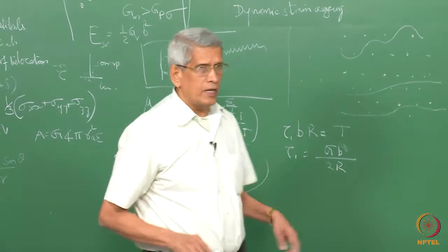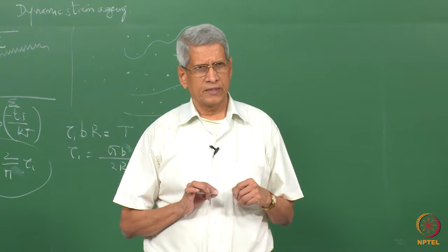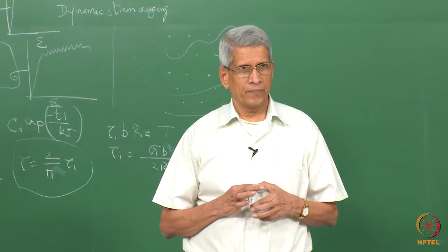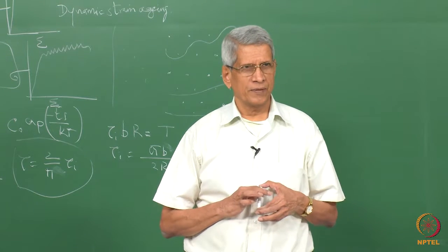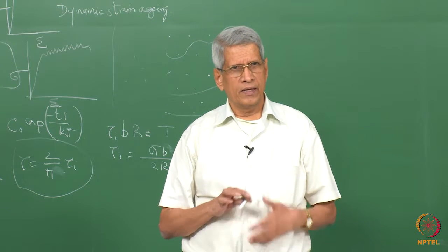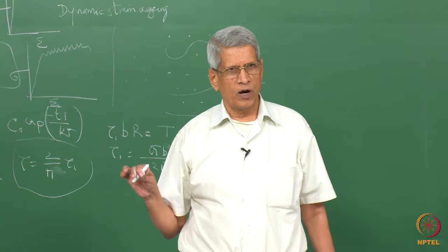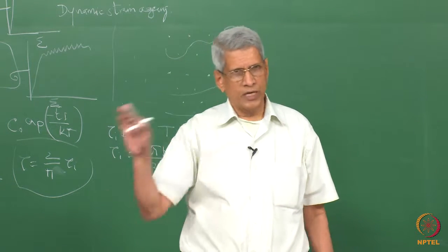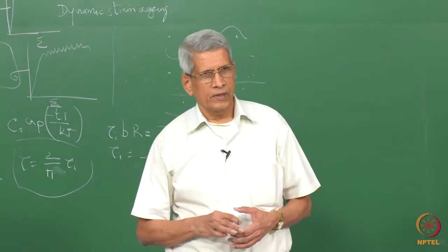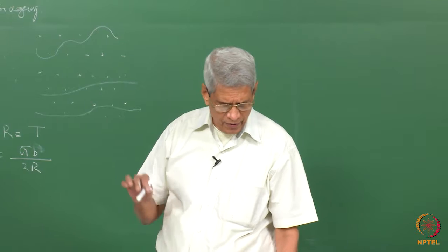Okay, this interaction. Suppose different particles are present at different places. There is an interparticle spacing which is going to be there. How do we take out the interparticle spacing? One way is to assume this is a randomly distributed particle, then the average interparticle spacing will be, if the number of particles per unit area is n, then 1 by root n. That will give us a value, okay. That's the way we can do it.